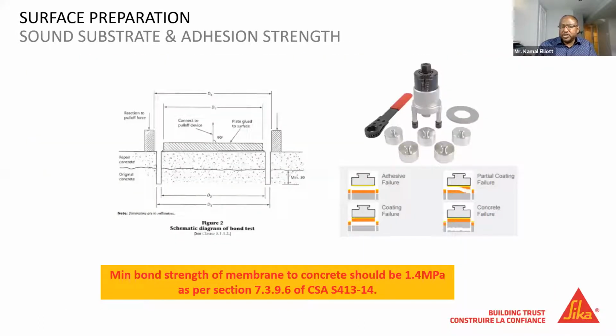The other aspect of the concrete is the strength. On the left, we show an example of a pull-off test where we're testing the tensile properties of the concrete. If concrete during construction was rain damaged, it would produce something that really wouldn't be sufficient for us to bond our system to. So we always want to make sure in our assessment of the concrete before we apply a coating that the concrete itself has sufficient strength. On the right, we show the bonding of the coating system to that concrete. And ideally, if you look closer at the bottom right, you see a concrete failure mode. That's ideally what we're looking for with our deck membranes and our coating systems.